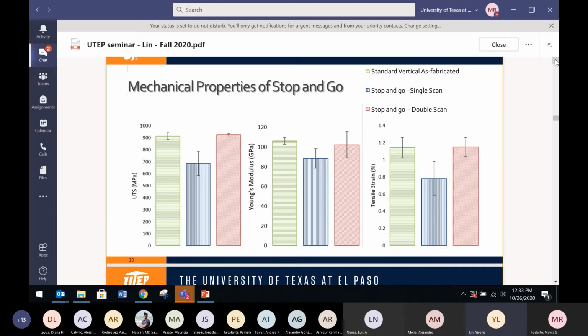So what we did is, once we put the print back into the printer, we did a double scan. In other words, we scanned the interface twice. That promotes the grain growth to continue to grow back. So you can see the red bar is showing the properties get increased a little, right? So we can somehow alleviate these issues. Next slide.